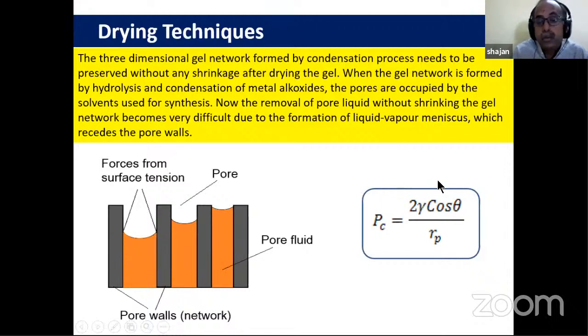So we have to see that if you increase the pressure, this will break. The walls of the material will break and it is completely collapsing. It should not happen. Therefore, we have to retain. We should be very careful while removing this. So here, this gamma is the surface tension between the liquid and the surface. And of course, cos theta is the interfacial angle. And all these, you as physics students know all these things.